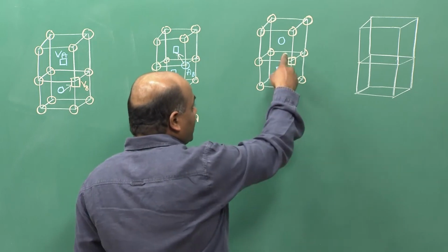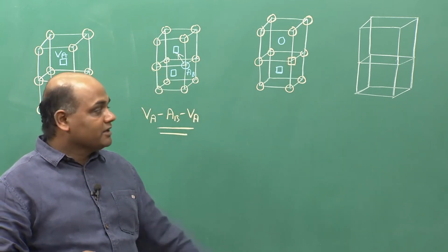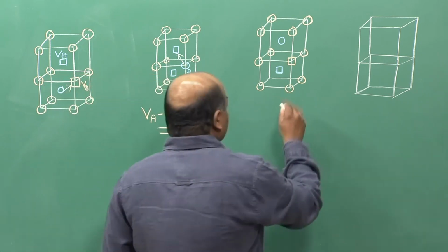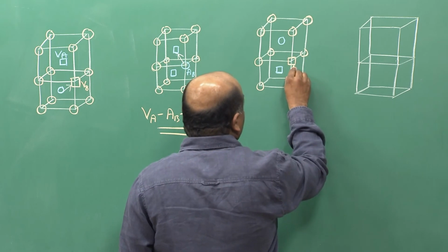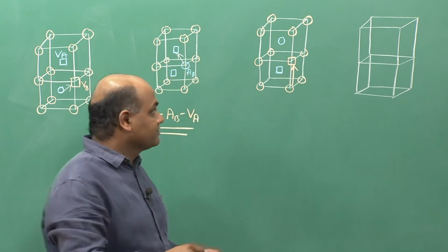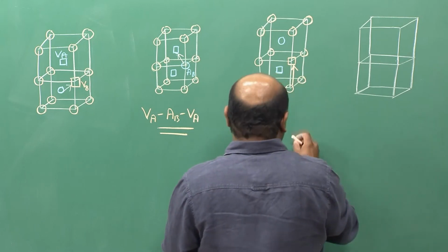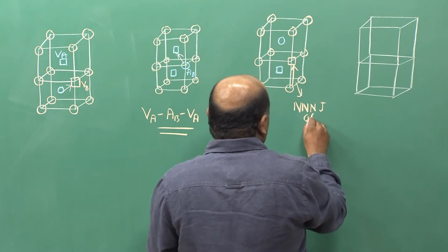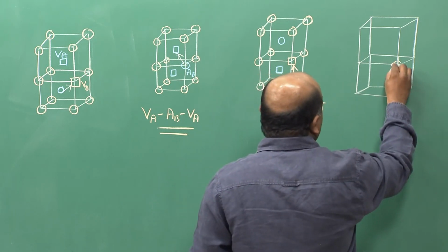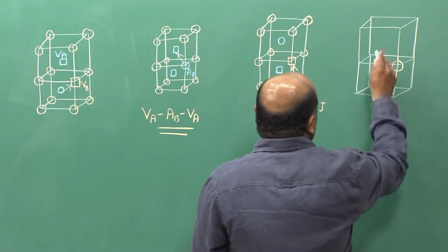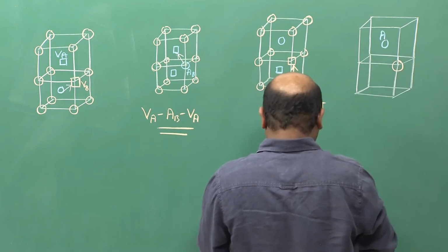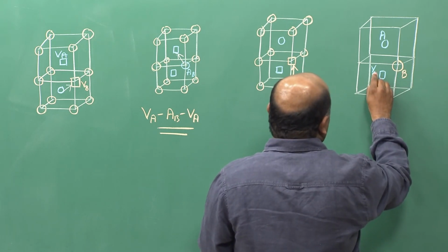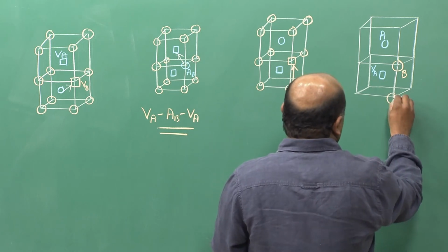and the B atom, being larger, can diffuse by triple defect jumps or next nearest neighbor jumps. So, now this B atom can jump into this site, this is a next nearest neighbor jump of B. So, B has now moved here, this is A, this is B, vacancy on A and vacancy on B.